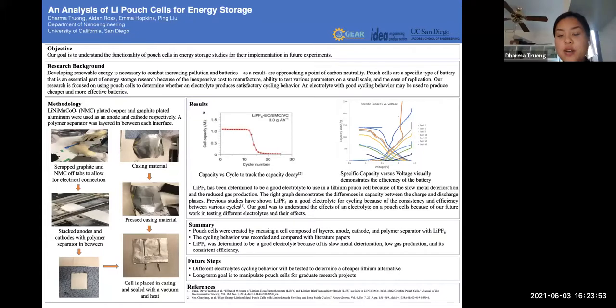And in summary of our research, we discovered that pouch cells were created by encasing a cell composed of layered anode, cathode, and polymer separator with lithium hexafluorophosphate. The cycling behavior was recorded and compared with literature papers, and we found that lithium hexafluorophosphate was determined to be a good electrolyte because of its slow metal deterioration, low gas production, and its constant efficiency.